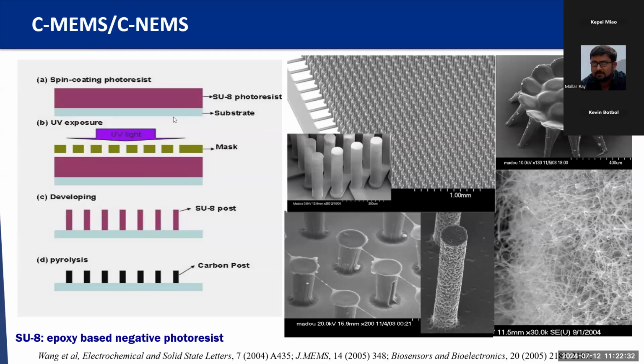Basically, the carbon MEMS technique we developed uses a photoresist. We can use either positive photoresist or negative photoresist, and we use photolithography processing combined with a carbonization process. The carbonization process, also called pyrolysis, is basically where you put the patterned polymer into the furnace, and in this furnace we try to avoid oxygen. So we have to either use a vacuum furnace or fill in forming gas or nitrogen gas. Avoiding oxygen in the furnace, we can carbonize the polymer patterns to carbon. This carbon is basically a glassy carbon.